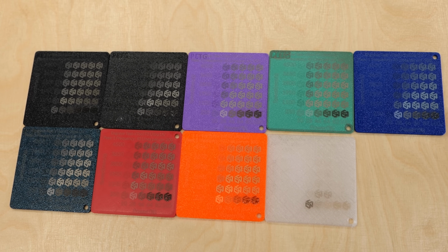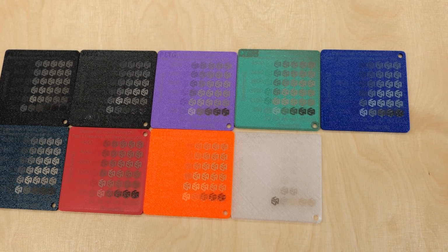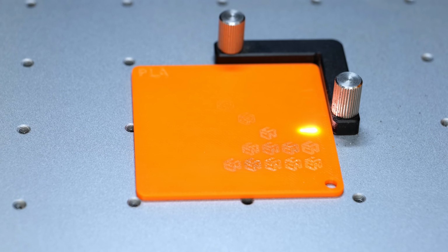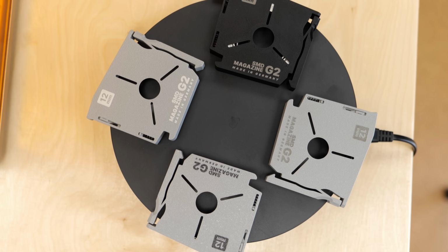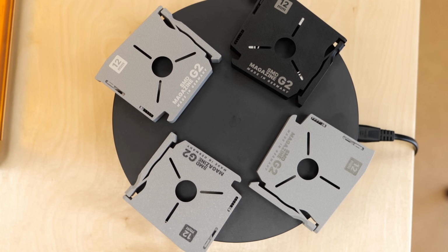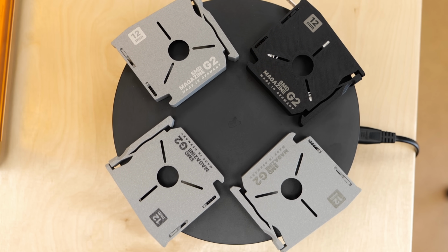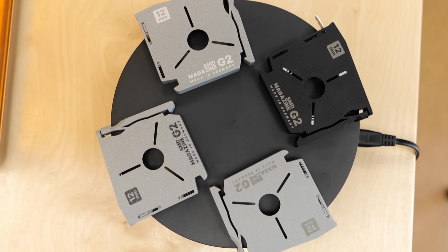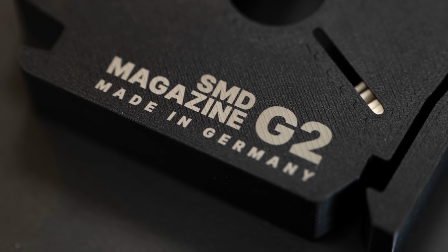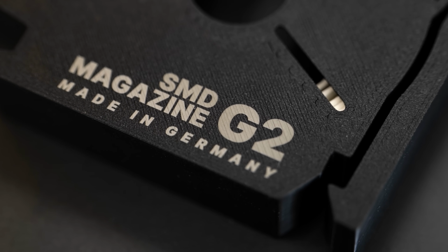Most materials seem to be markable if you tune the parameters, but the effect can be brutally different. And sometimes the best solution is not to keep fighting the laser settings. Sometimes it is smarter to change the filament color or even just the filament supplier. MOPA and UV can work, though the UV laser was easier to get right in my tests.